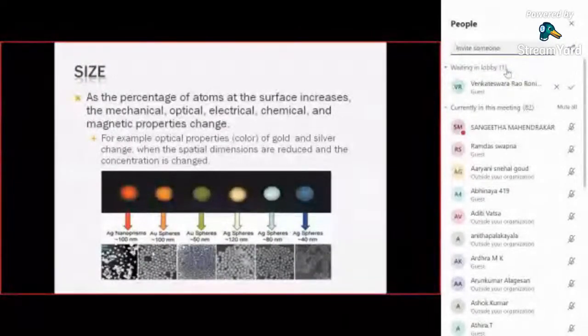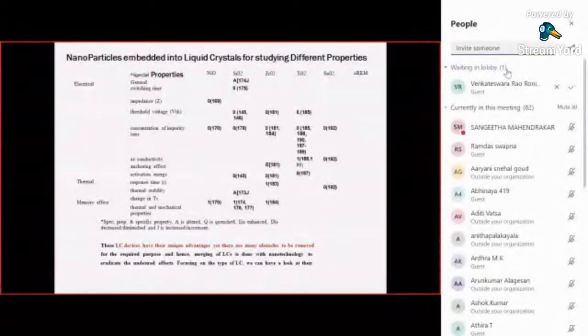Now I am talking about the need of nanomaterial, and why nanomaterials are embedded into liquid crystal for studying different properties. These are the main properties we can study in the field of liquid crystal for fabrication of displays: switching time, impedance, threshold, concentration of impurity ions, AC conductivity, anchoring effect, activation energy. These are some thermal parameters, and we can also investigate memory effect with respect to temperature, or by changing its mechanical or thermal property. The work has been done by choosing particles like nickel oxide, silicon oxide, zirconia, titanium. A lot of particles are there.